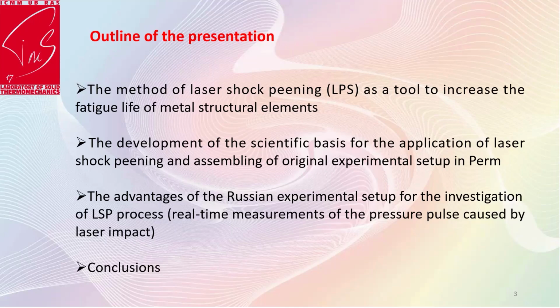assembled in my institute. From my point of view, it has at least 2 advantages. We can measure stress, strain, and impact in real time, and we can measure the distribution of residual stress. So we can investigate all peculiarities of these processes and find the optimal region for treatment. Finally, I'm not going into detail about structural investigation. It's quite interesting, we can discuss. There are still a lot of open questions, but I will show just results for samples with a stress concentrator. For me, it's quite amazing: we can increase fatigue life 10 times. If you find the optimal regime, it's not 10, 20%, it's times.